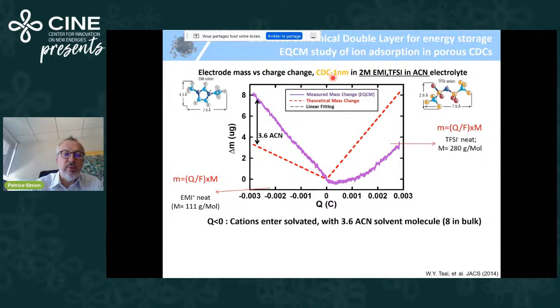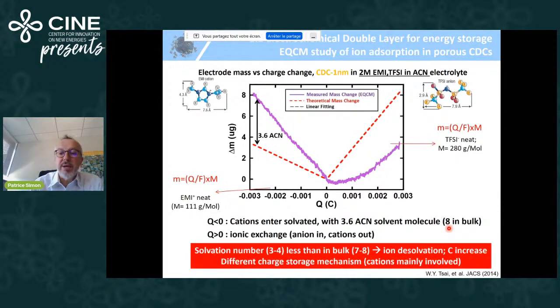So we have carbon pores of 1 nanometer pore size. And during negative polarization, cations enter with 3 to 4 solvent molecules. Knowing that cations are surrounded by 8 more solvent molecules in the bulk, then we can say that this is an experimental evidence of partial desolvation.